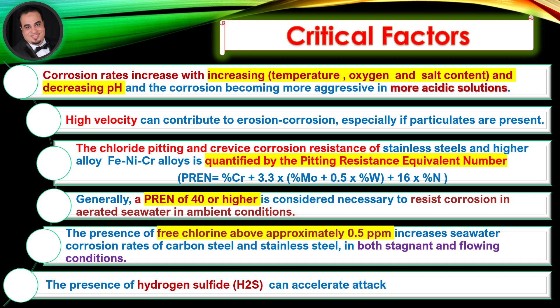Generally, a pitting resistance equivalent number of 40 or higher is considered necessary to resist corrosion in aerated seawater at ambient conditions. The presence of free chlorine above approximately 0.5 parts per million increases seawater corrosion rates of carbon steel and stainless steel in both stagnant and flowing conditions. The presence of hydrogen sulfide can accelerate attack.